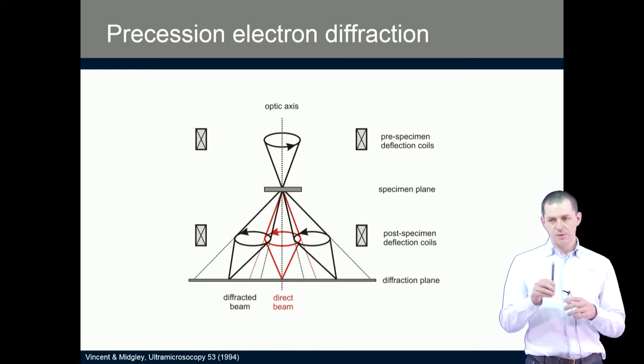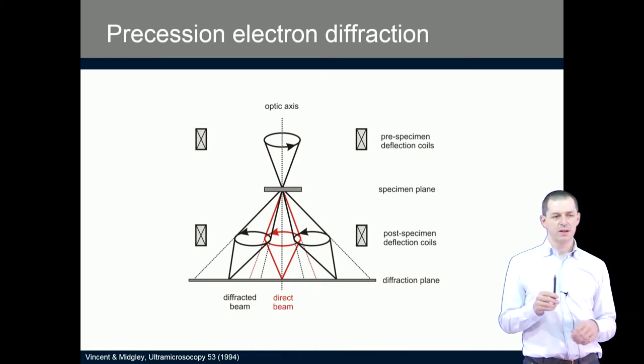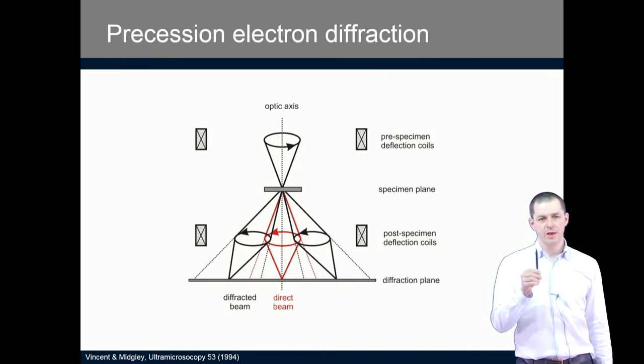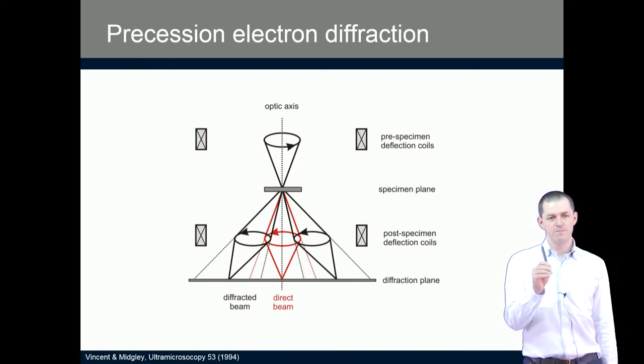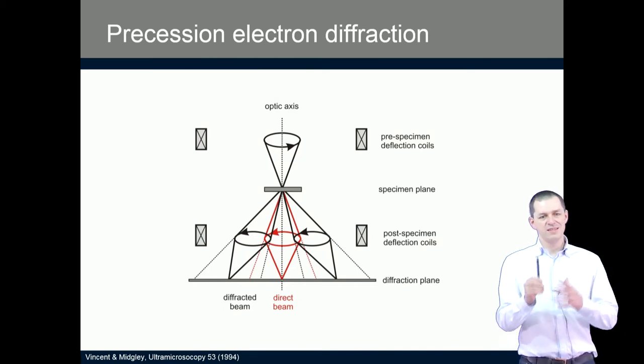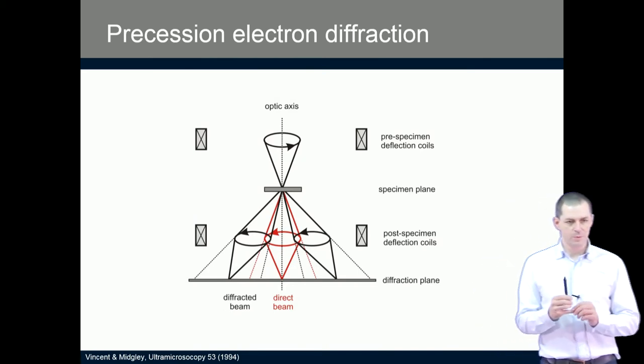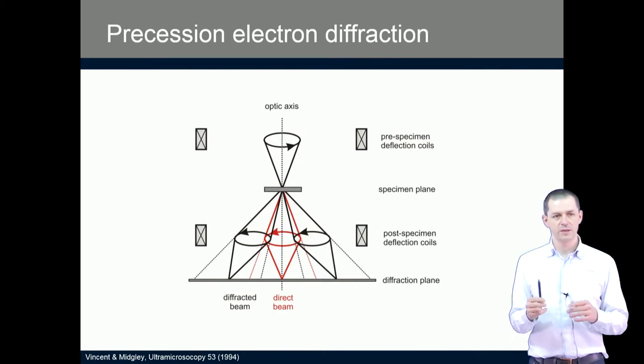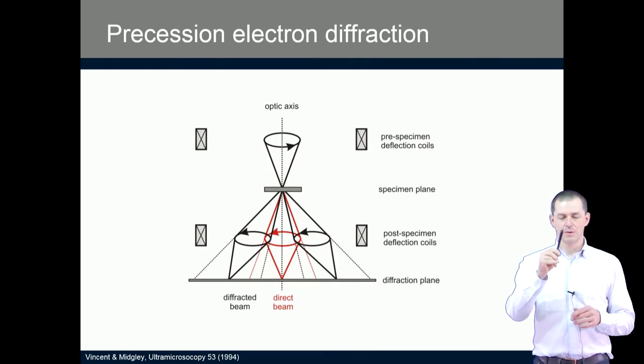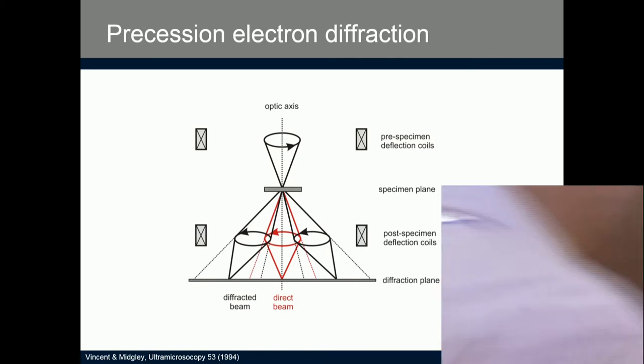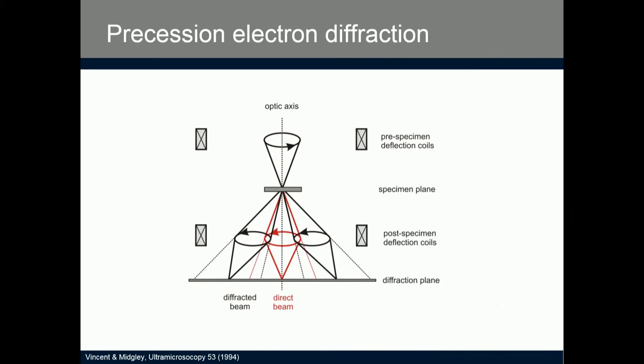The method is based on an idea that an electron beam does not have to be stationary in the microscope, but its trajectory may be easily modified by the electron optics, so it may be made to move along a precession. It may be moving on the surface of a cone, so it can perform a precessing motion, so the beam, instead of falling on the sample like this, is moving and falling on the sample like this. This is shown in this picture.